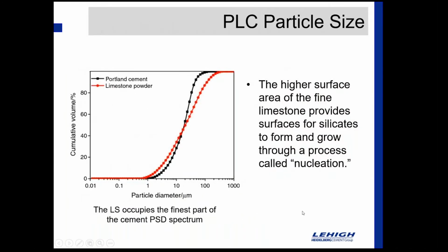So I wanted to talk about that just a bit on why we see some of these performance enhancements from the Portland limestone cement. One of the big ones is when we look at the particle size distribution of a PLC, you can see on our red line here, that's the particle size spectrum of limestone powder in that mix. And what it does is extend the particle size distribution of the Portland cement more toward that very fine end. The limestone is very soft, so it grinds a lot easier than the clinker that is produced through a kiln. And so you end up with a higher fineness material, but that higher fineness doesn't change the overall water demand or slump performance of that concrete.